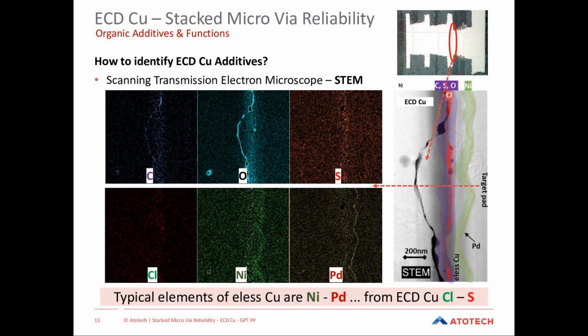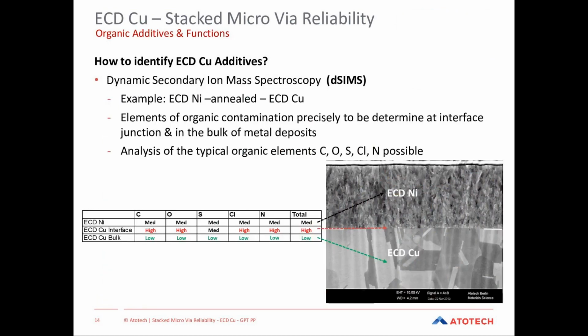But with this STEM method, we can also identify chloride, sulfur, oxygen and carbon. Nitrogen was not visible here, so it's not shown as an indication. But with this scanning transmission electron microscope, you already have a chance to find out, okay, do I have typical elements from electroplated copper processes in the interface? Or are these interfaces free from these elements? So you know better what process you have to troubleshoot later, if you know what elements are typical for a process.